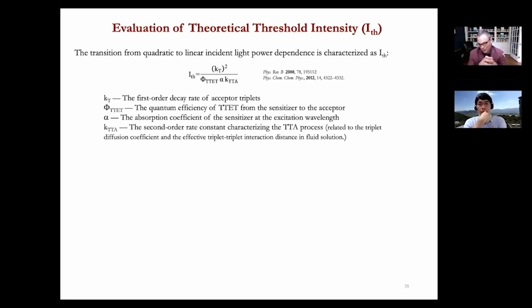That's a self-quenching mechanism as well. Our zirconium compound does not aggregate. We did all the NMR experiments to prove it. It also does not engage in triplet annihilation with itself. So it basically circumvents every single competitive pathway of what I talked about today. So I think our zirconium sensitizer just doesn't have these deleterious pathways.